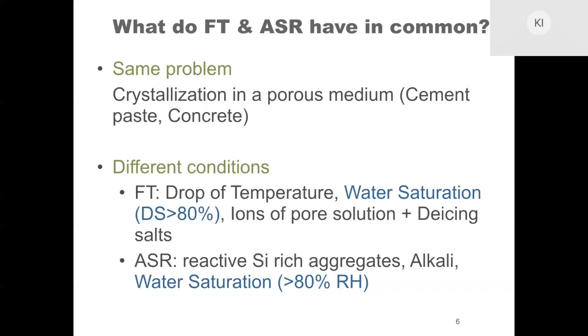In the case of freeze-thaw, the problem is the drop of temperature in the winter. And this problem is getting worse as we are adding de-icing salts on the surface of pavements to prevent accidents. This is making the problem even worse. An important point is that in order to have this type of damage, we need to have a high degree of water saturation. So the material needs to be saturated with water, otherwise damage is not observed.